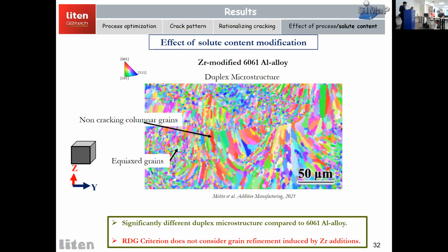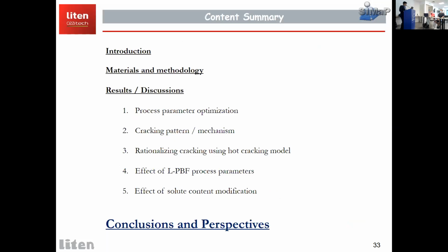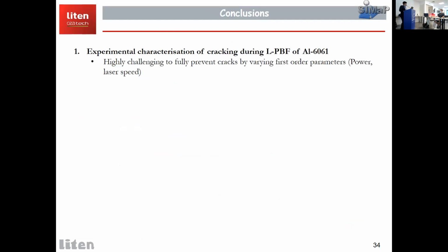So, okay, we have studied processing optimization. We have studied a bit of solute content modifications. Now, based on all the study, let me present the final conclusions of the work. Based on the experimental characterizations of the 6061 aluminum alloy produced in L-PBF conditions, we concluded that it is highly challenging to fully prevent cracks by just playing with the first order of process parameters. We know that cracking occurs particularly at high angle grain boundaries and exactly in the center of melt pools.